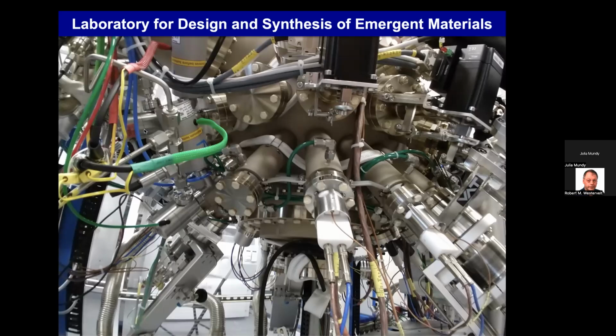So we do have various things in our lab. We do X-ray diffraction. It really depends on what the materials are. Sometimes measuring the transport is exquisitely sensitive. You have a metal insulator transition and it drops 50 degrees if you're slightly off composition. So there are various different techniques like that. Transport is a powerful way to do it, but you can also do structural measurements as well.